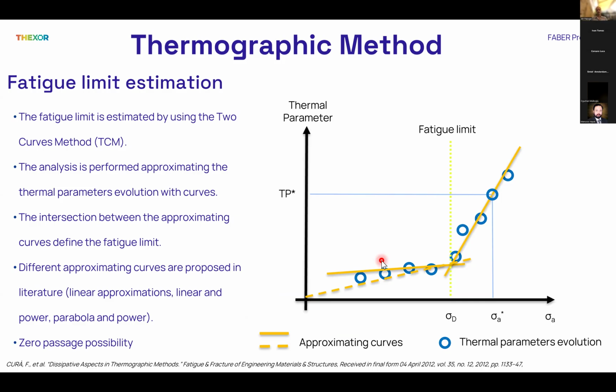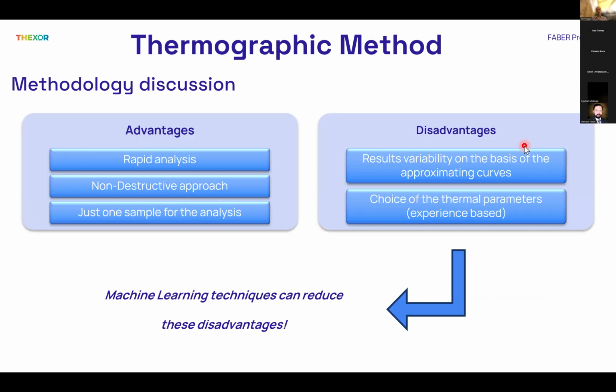So at the end, the most appropriate choice in terms of approximating curves or thermal parameter depends on the experience, on the material, or on the load applied during the fatigue test, or in general, the evaluation is done on the basis of the thermal parameters' evolution obtained during the fatigue test. So the thermographic method has advantages in terms of rapidity and a non-destructive approach.